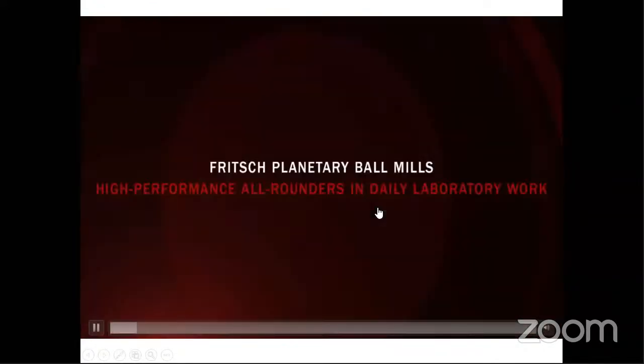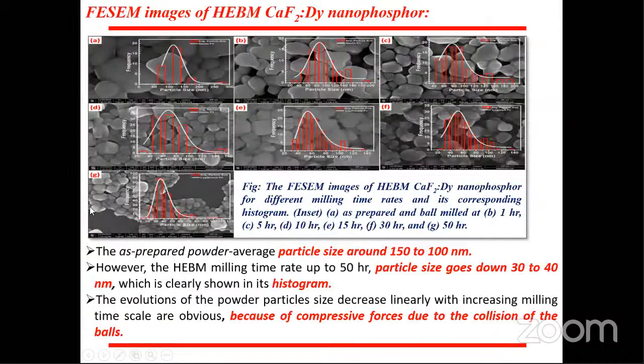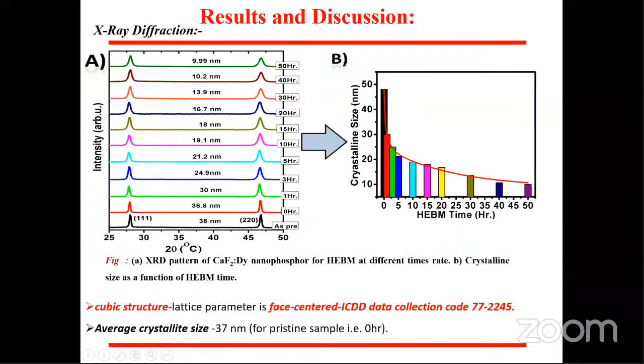Always, large-size particle material shows a highly sensitive behavior in the area of thermoluminescence, but the dose range response is very small, below 1000 gray, or we can say below 1 kilogray. But if we reduce the particle size, then we get a high dose range response.